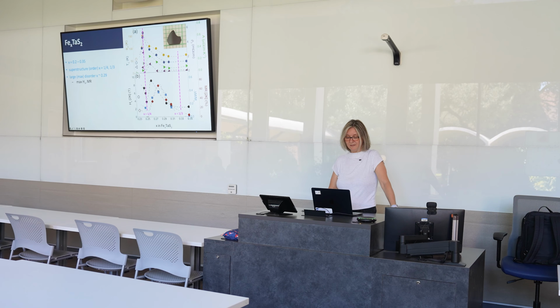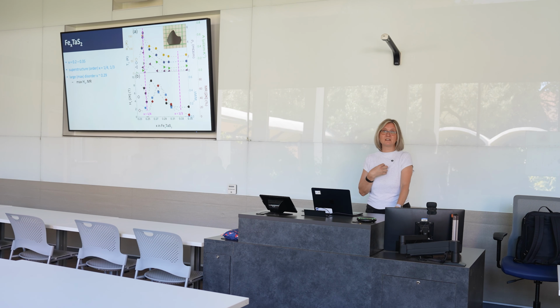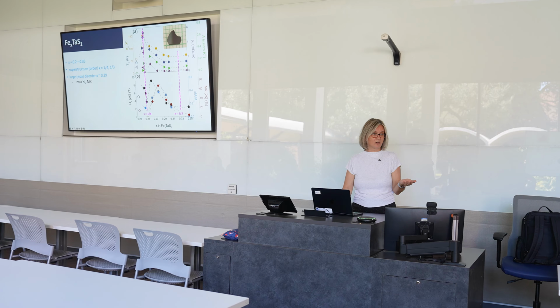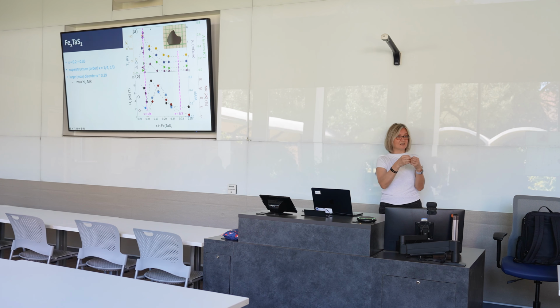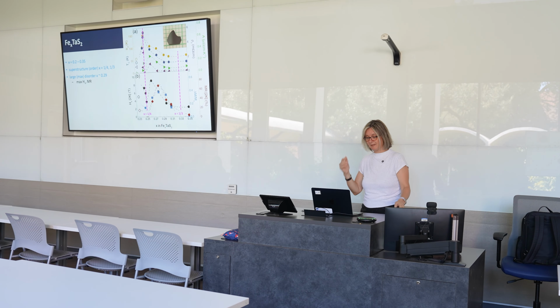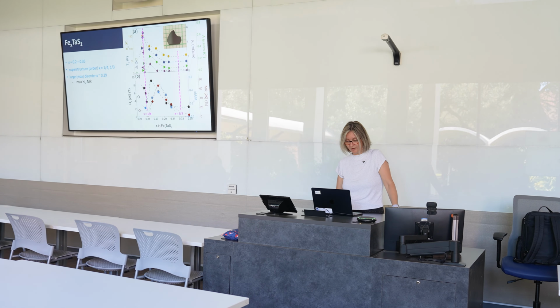But in any event, you see how the physical properties don't change monotonously as a function of composition. And to me, the most striking is the fact that the ordering temperature varies so much. So at x equal a quarter, the ordering temperature is 160. On the sides, it's down to 40 or less. According to what I just said, that if the distance is smaller, the coupling should be stronger, the temperature should be higher for higher compositions, and yet that's not the case. So that's still something that we don't understand, we're pondering on.